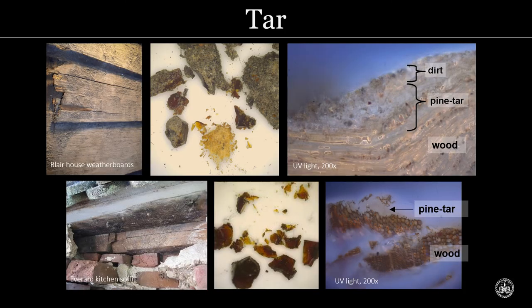In cross-section, tar is very ephemeral, especially when it wasn't pigmented. So here are two examples where we found unpigmented tar on our buildings. These were in areas that had been protected by later additions, so for many years they were hidden and preserved. Now, both of the surfaces were so dirty that it was difficult to see any coating, but when I brought the samples back to my lab and looked at them with low power microscopy, I could definitely see these fragments of a reddish brown resinous material.